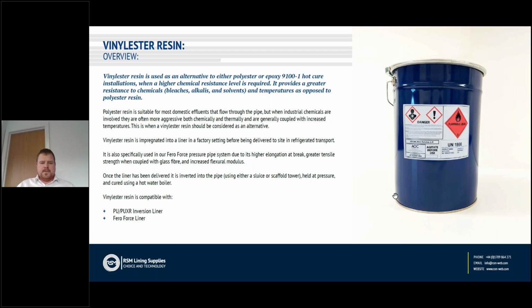Once we have impregnated the liner in a factory setting, it's delivered to site and usually inverted into the pipe using a sluice, scaffold tower or other pressure vessel, cured using a hot water boiler or steam boiler, both of which are available from RSM. The compatibility of vinyl ester is a little bit more limited than some of our other materials, but we stock an extensive range of polyurethane coated liners with extra resistance, extra passive coating for pressure applications, and also the Ferroforce material.